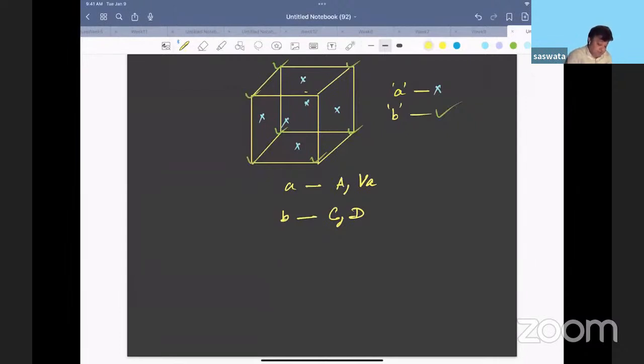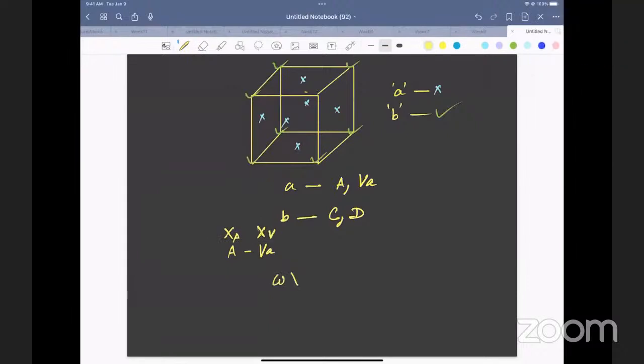We write a regular solution model. So there, how do you generally do it? Say, for example, if I have just a binary model which has pure A and vacancies. So we are basically thinking of vacancies as substitutional elements, isn't it? The atoms are there, and where atoms are missing, we call it a vacancy. Now if I have my mole fraction of atoms as XA and the mole fraction of vacancies as XV, then you have omega XA XV.